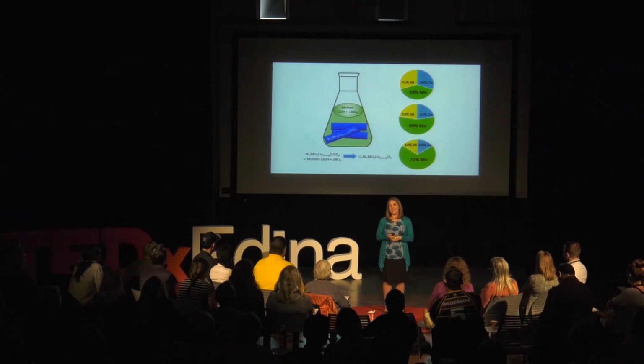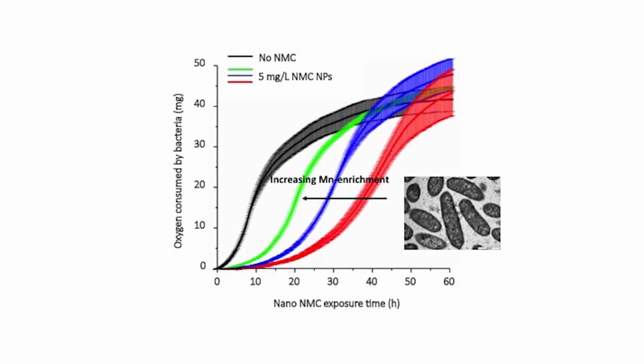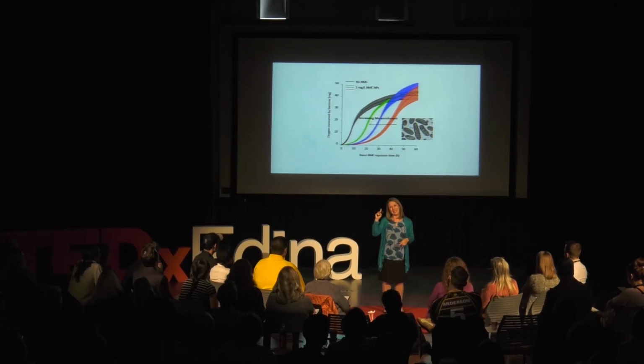And we were really excited to see that when we put them in with the Shewanella, as we decreased the nickel and cobalt, we saw a commensurate decrease in the toxicity in the bacteria. That arrow is showing you bacterial function moving towards that of a nanoparticle-free control. So this is a great example of proactively designing materials so that we can get maximal technological impact and minimal environmental consequences.